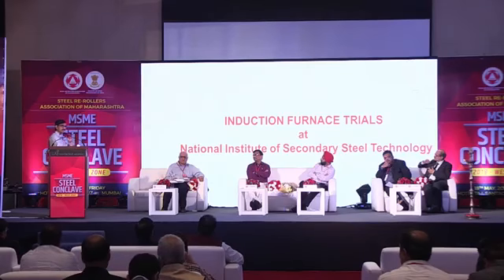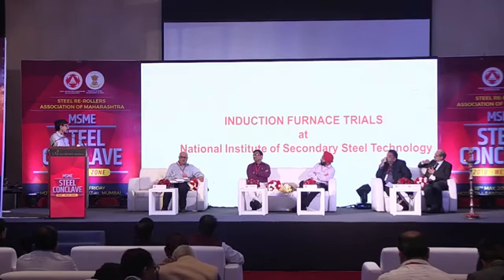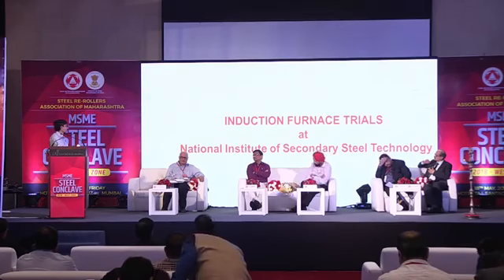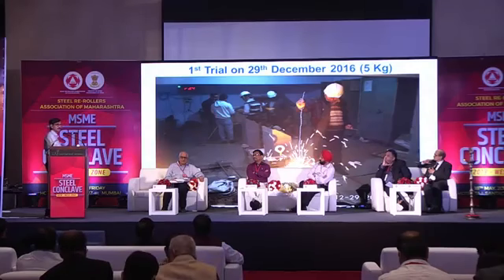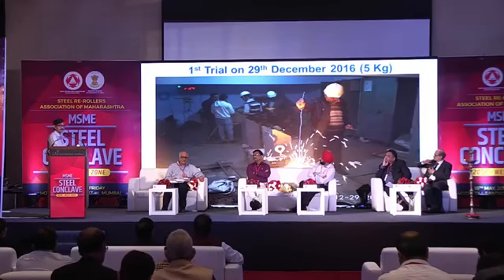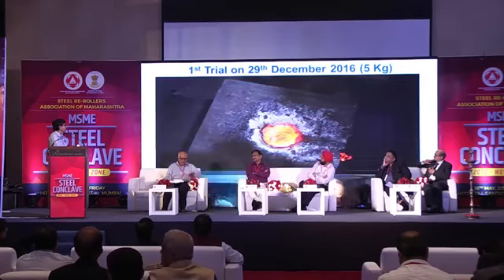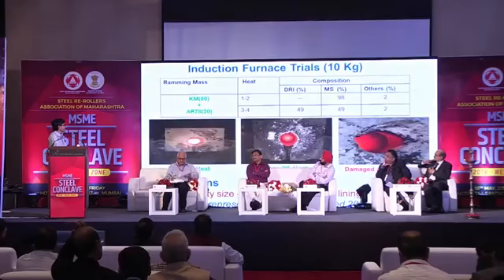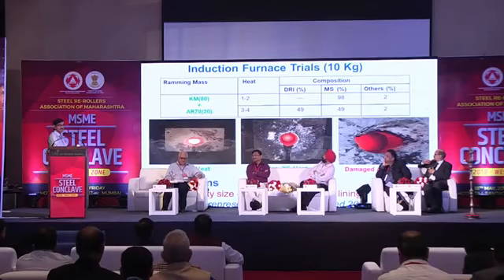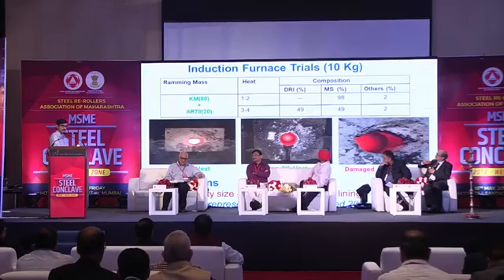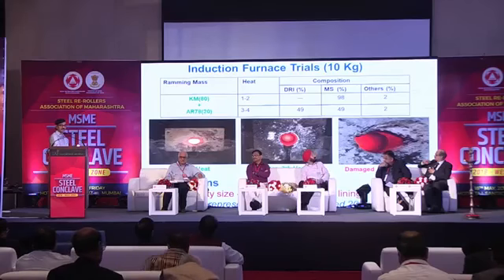Okay. Now based on our laboratory findings, we have carried out the trials at the National Institute of Secondary Steel Technology. We first started in a 5 kg induction furnace in December 2016. You see, I can quickly pass through some of these. At that time we got hardly 4 heats initially, because the 5 kg induction furnace cavity size is very small, so when you put in the flux, the flux instantly reacts with the refractory. And we used a maximum of 49 or 50% DRI.